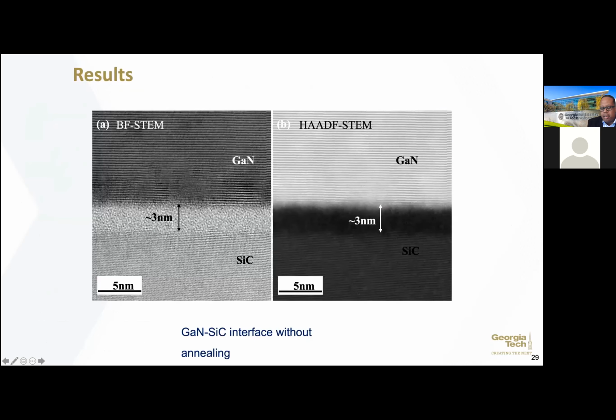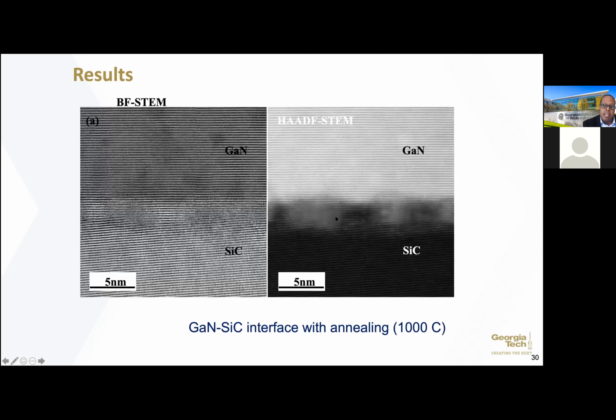So the interesting thing here is that we're trying to get rid of the interface of the aluminum nitride, but going into doing this plasma activated bonding, you damage this interface and you end up getting an amorphous region of silicon carbide. So we still don't get away from having this interfacial region between the two materials. What you are able to do is anneal this at about 1000 degrees C, and you start to get recrystallization of this interface. It's still not perfect, but this is something that can be worked on in terms of the manufacturing processes in order to improve that overall interface in terms of the crystallinity.